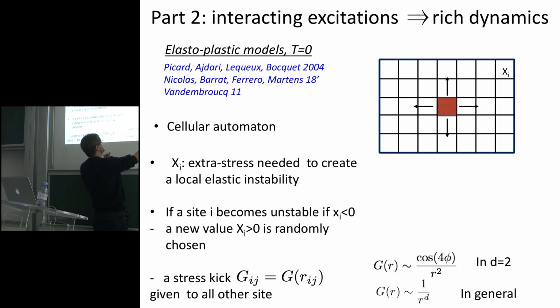Because if this guy relaxes, it's a plastic strain, so it will change the stress elsewhere in the material. So those different blocks are actually interacting. They are interacting with some propagator Gij, which essentially depends on the distance between i and j, and also has some angular dependence, so it's not clear here. But this square relaxing changes stress elsewhere. What you need to remember is that this change of stress decays like 1 over R^d, like a dipole, essentially, but it's changing sign. Some regions are stabilized, other regions are destabilized.